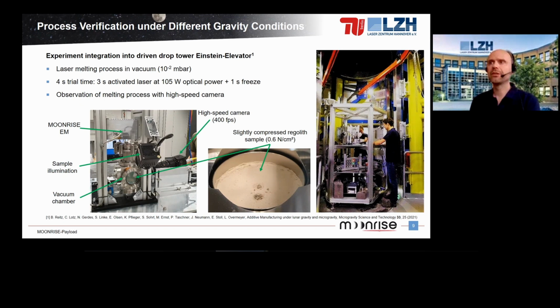Here in Hanover, we have the so-called Einstein elevator, which is a driven drop tower. With this drop tower, you can also simulate lunar gravitation. And we have 4 seconds trial time. We activated the laser for 3 seconds at 105 watts of optical power. We have a little bit shorter time than in the experiments before. Therefore, we had to go higher with the power, and 1 second to cool down the melt.